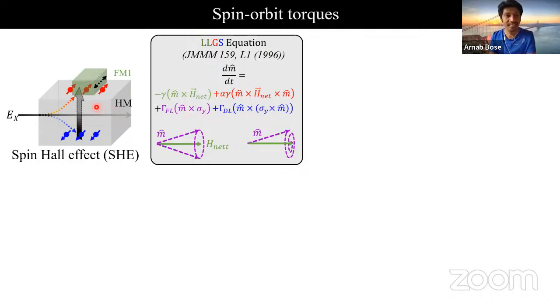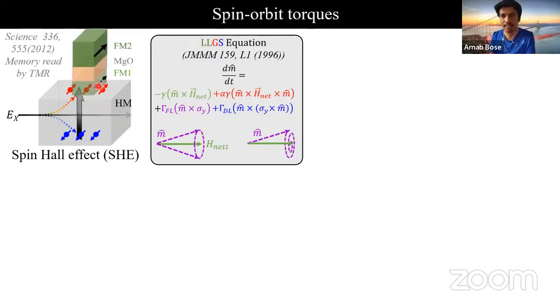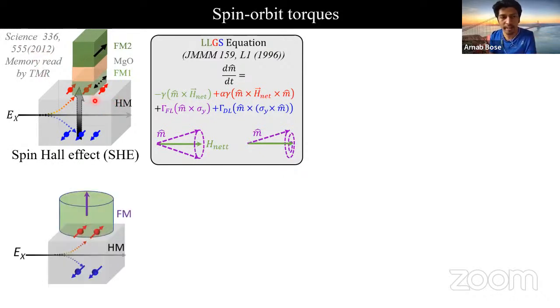Now, if the spin current density is enough, eventually it can switch this magnet and we can read the magnetization state by measuring TMR of an MTJ fabricated on top of the heavy metal, which has been reported in this pioneer work. So not only the in-plane magnet, the spin orbit torque can also be useful to manipulate the out-of-plane magnet. But for the out-of-plane magnet, it is not very efficient for the deterministic switching because the accumulated spins are orthogonal to the magnetization.